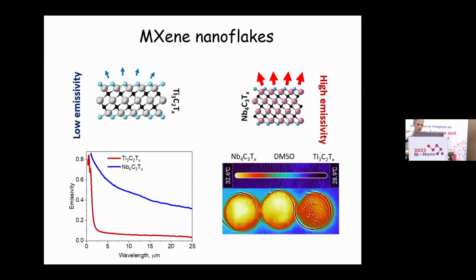They have different thermal emission dependent on the wavelengths shown here. Titanium MXenes have very low thermal emission. That means that they can work as a passive heating material, because they do not emit heat into the environment, and most heat is kept inside the system. And here you can see an illustration of thermal emission of different MXenes. So the middle part corresponds to the emission of the solvent without any nanoparticles. The left part is solvent with niobium MXenes, and the right part is solvent with titanium MXenes. So we can see that the emission of the niobium one is higher than the emission of the titanium MXene dispersion.